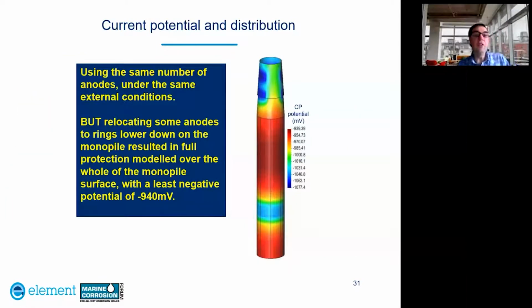However, using the same number of anodes under the same external conditions, but relocating some anodes to rings lower down on the monopile resulted in full protection modelled over the whole of the monopile surface with a least negative potential of -940 millivolts. And that's shown on this model here, which shows that the least negative potential is -940 millivolts.